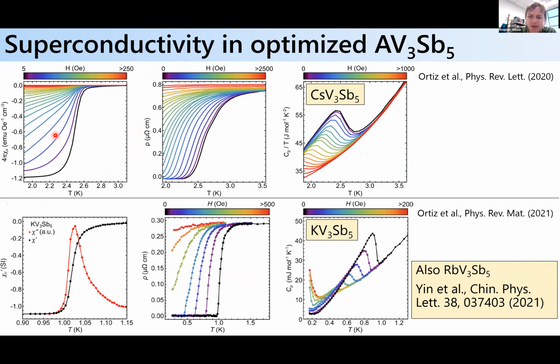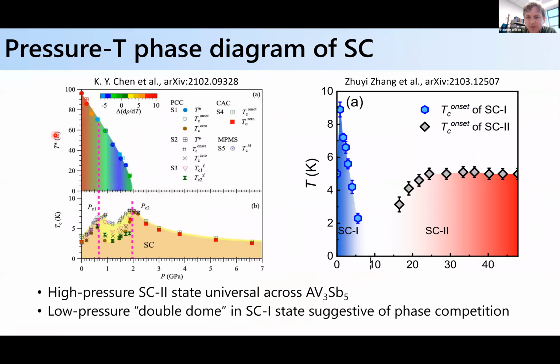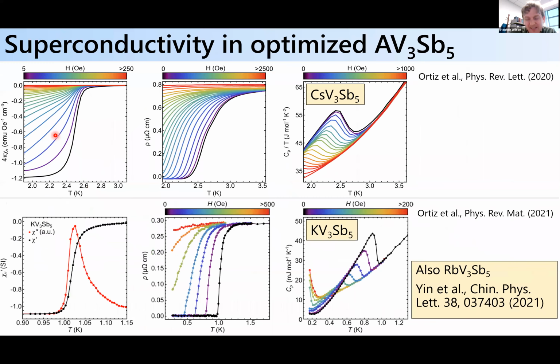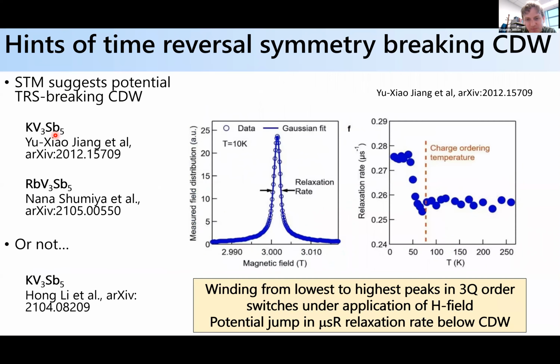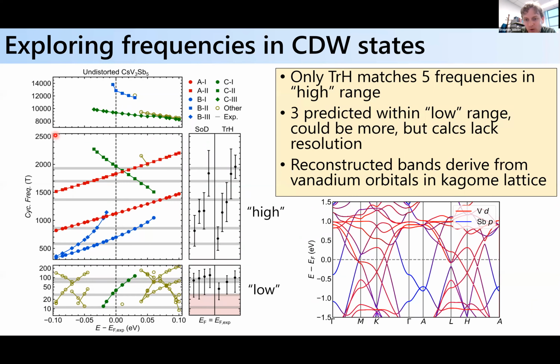So, the primary band structure. If you do an orbital projection, basically at EF, things primarily come from the vanadium orbitals. So this is the orbital projection. There is some mixing, a little bit of mixing from the antimony sites as well. But the question is, what is leading to the situation which is less correlated, or is it mainly because of the vanadium?